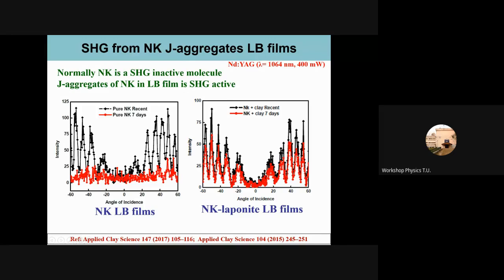But when we incorporate clay in the system, you can see that even after 7 days, or we studied more than that also, the change in intensity is less with respect to the freshly prepared one. That means the presence of clay enhances the mechanical stability. And this kind of second harmonic phenomenon is important for applications like SHG microscopy, or maybe laser applications. There are several examples also.